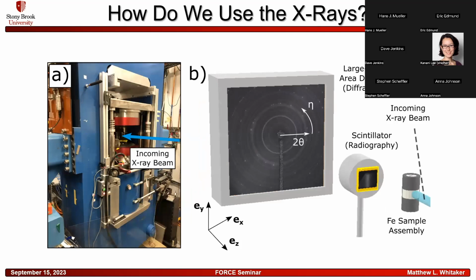So here again is a picture of the press with the incoming X-ray beam coming from the right. And if we look all the way on the right here, we have the X-ray beam going in and entering the sample cell assembly and hitting the sample. And then the exiting X-ray beam first hits the scintillator, which gives us an X-radiographic image of the sample. And then the diffraction goes around the scintillator and hits the large area detector in the back. And that's where we collect our X-ray diffraction data.